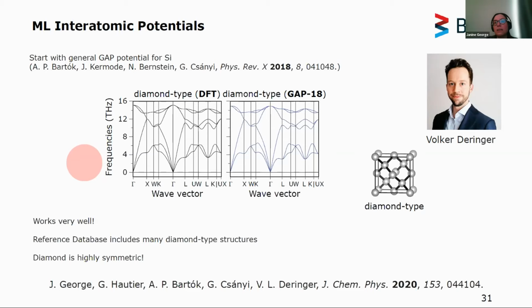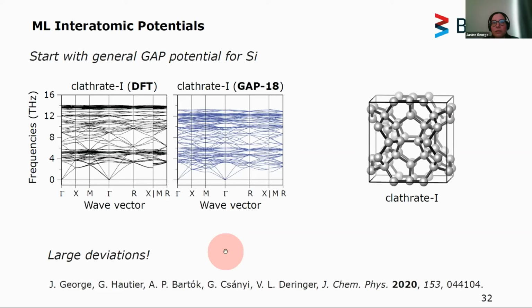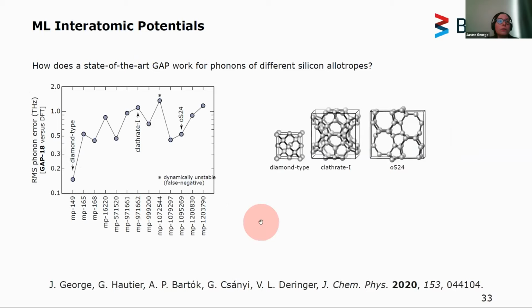When we went on with more complex structures, such as clathrate one, we already saw much larger deviations. And we then also took 11 other crystal structures from the Materials Project database and computed a phonon error along this phonon band structure. It should be, of course, in the ideal case at zero. It should be fitting very well to the DFT data. But we found an error that was always larger than for diamond type silicon for these other more complex crystal structures.